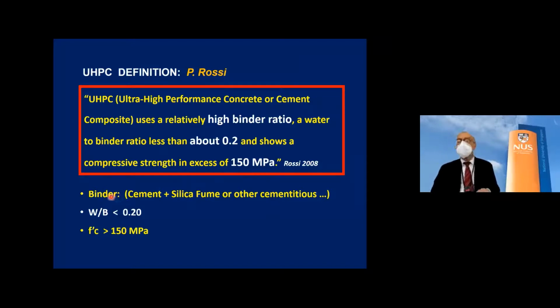High binder ratio: the binder is essentially your cement, but if you are using silica fume or other cementitious additive, well, that's the binder. When you say high binder ratio, you could translate that to high cement content compared to the aggregate, so it's all by ratio. Water binder ratio less than 0.2.